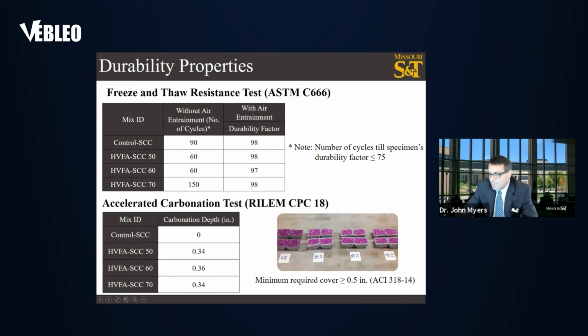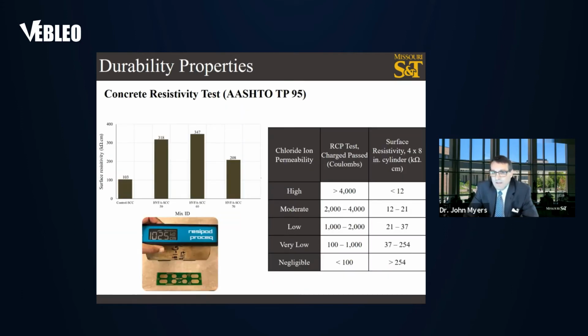The fly ash ones had higher carbonation depths. That can be associated with the fact that we used hydrated lime to help the early age strength gain of the mix designs. The surface electric resistivity test was also undertaken to provide a rapid indication of the concrete's resistance to the penetration of chloride ions.